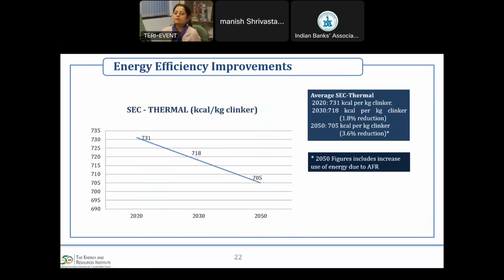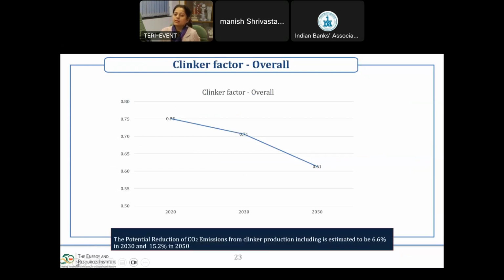So in this, it is projected that specific energy consumption, which is the thermal energy consumption for the production of clinker, is going to reduce from 731 kilocalories per kg of clinker to 705 kilocalories per kg of clinker. So that means the consumption of thermal energy is going to reduce, and we project that the Indian cement sector can embrace these technologies, adopt more energy efficient practices and achieve lower emission intensity targets by 2050. Similarly, the clinker factor, which is the amount of clinker as a percentage, would also reduce from 0.76 to 0.61 up to 2050, and it has a potential to reduce up to 15% of emissions by 2050. Next slide.